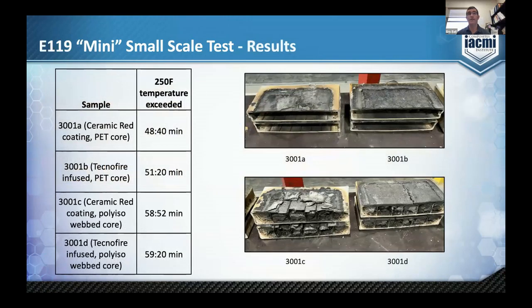So here's the test results of the mini test. The ceramic red coating went 48 minutes before the temperature exceeded, and the Technofire went 51 minutes. And then the polyiso webbed core went 58 and 59. This was a ceramic red, and this is Technofire. Now, if you look over here on the pictures, you can see again where the material with the ceramic red kind of fell apart and it really burned up. The temperatures get super hot, like up to 1800 degrees. So the Technofire provided some pretty good protection as a thermal break.